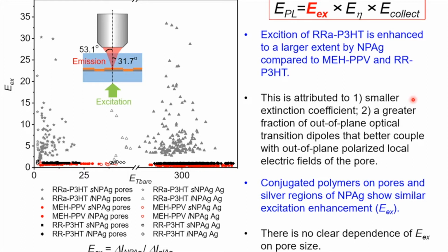So we attribute the large enhancement of the excitation to a smaller extinction coefficient of regiorandom P3HT compared to the other two polymers, so there's more ability for it to be enhanced by the metasurface due to increased absorption enhancement. And then a greater fraction of out-of-plane optical transition dipoles, which couple better to the out-of-plane polarized local electric fields of the pores. The conjugated polymers on pores and silver regions of the nanopore silver interestingly showed very similar excitation enhancement for the regiorandom P3HT. And in general, we found no clear dependence of the excitation enhancement on pore size.